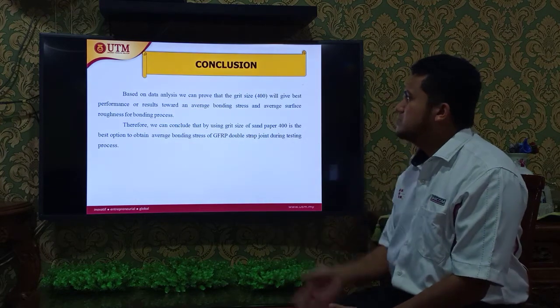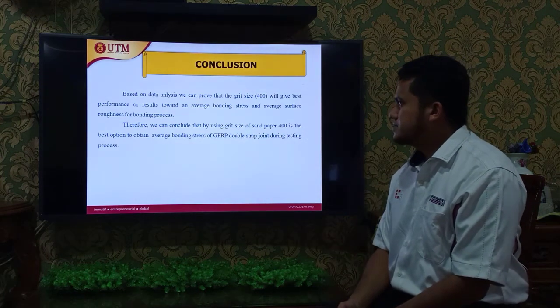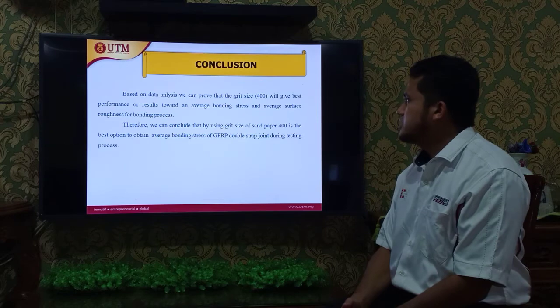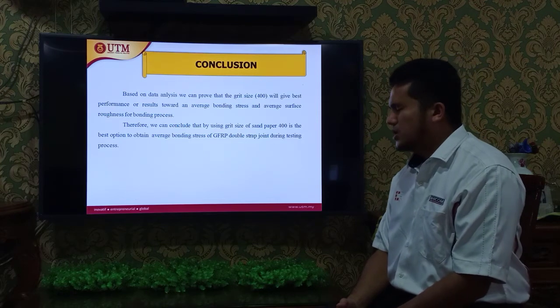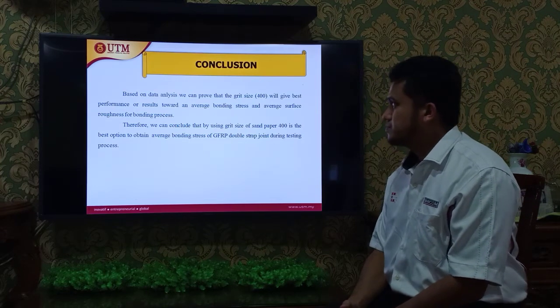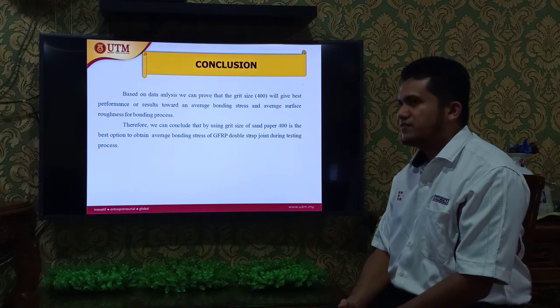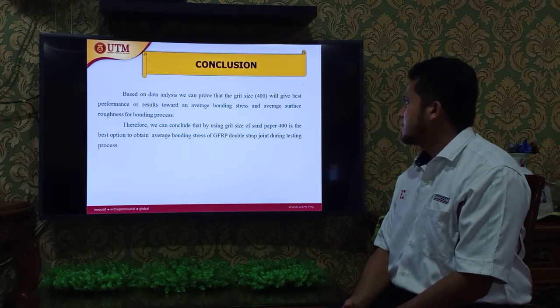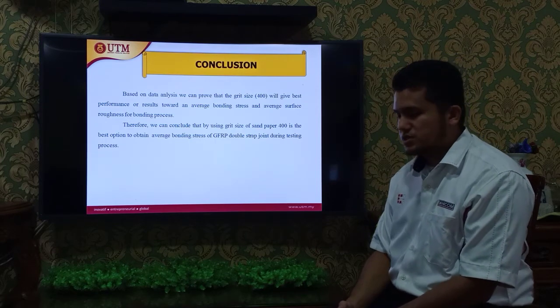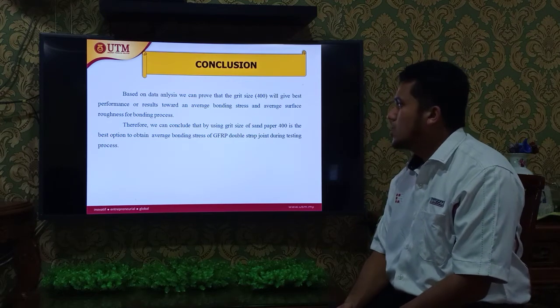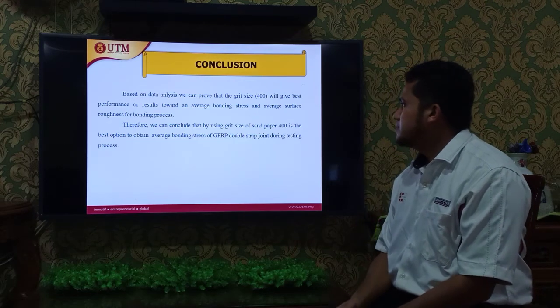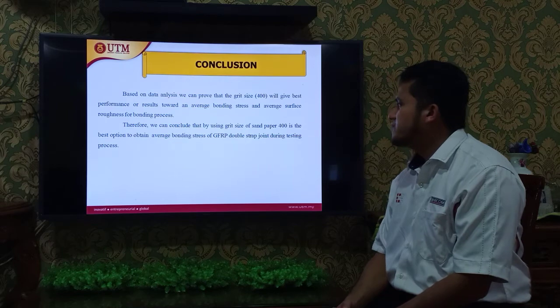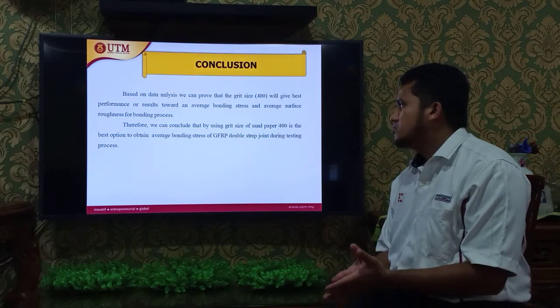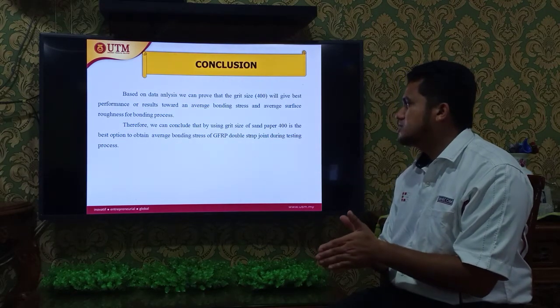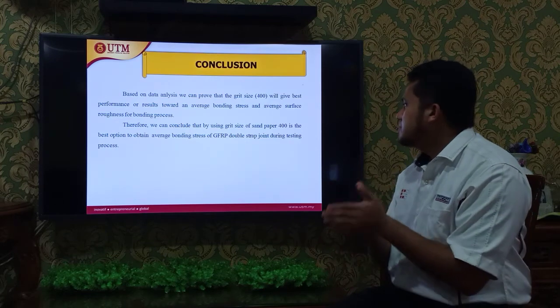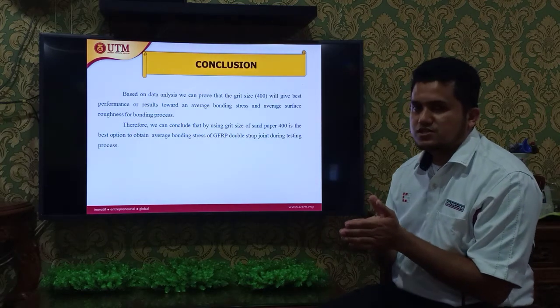For the conclusion, based on the data analysis, we can prove that grit size 400 will give the best performance towards average bonding stress and average surface roughness for the bonding process. Therefore, we can conclude that using grit size 400 sandpaper is the best option to obtain the average bonding stress of a GFRP double strap joint during the testing process.